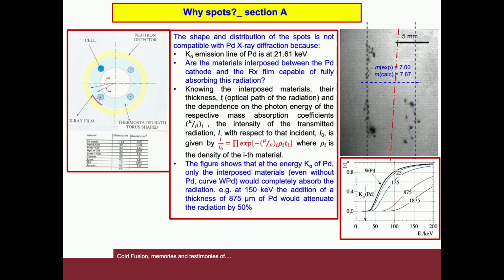The figure shows that at the K threshold energy of palladium, only the interposed material, even without palladium, would completely absorb the radiation. In fact, we see that at 21.61 kiloelectronvolts on the WPd curve, the transmitted intensity is 0. Therefore, it means that the interposed materials would totally absorb that radiation.